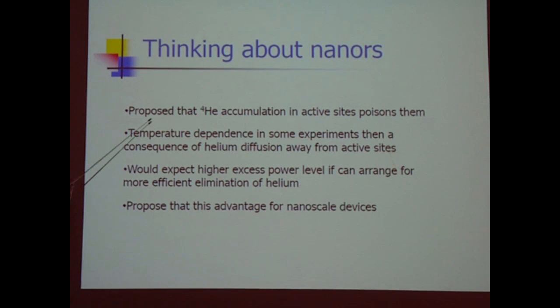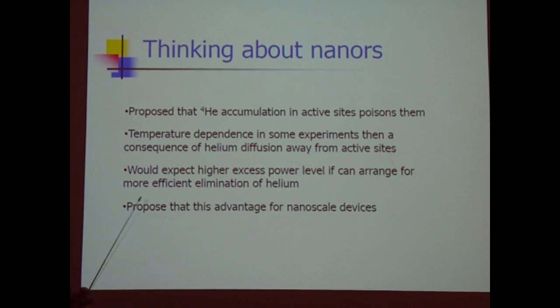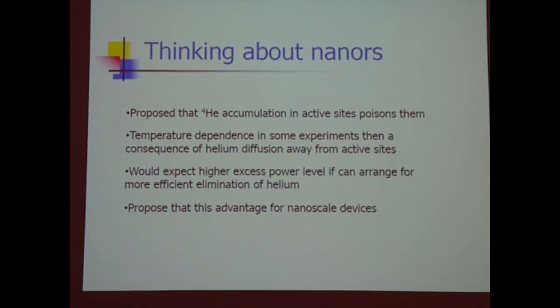So the question is, if helium-4 accumulates in active sites and poisons them, in the sense of not allowing further reactions to happen when all the active sites are filled up, and if that's responsible for the temperature dependence, then maybe if you make the distance between the site and the nearest surface where you can get rid of helium-4 smaller, you'd be able to work at higher power, because dumping the helium-4 would be far more efficient in a smaller scale system. So I'm proposing that this is perhaps the physical source of the advantage of nanoscale systems.